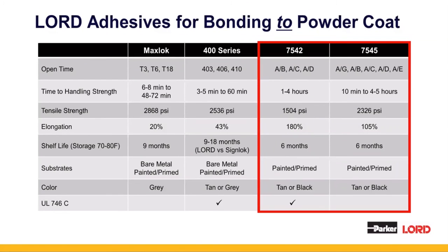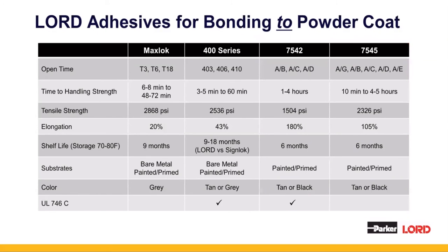The next two recommended products that we have are 7542 and 7545. These are urethane-based adhesives and they grip very, very well into paint. More often than not, these are our first recommendations for bonding to powder coat paint or primed or painted metals. The big difference between the two is that the 7542 has UL 746C approval, and it has a lower viscosity, which makes it great for going into tighter tolerances. The 7545 is more of a paste consistency. It has a lot higher viscosity.